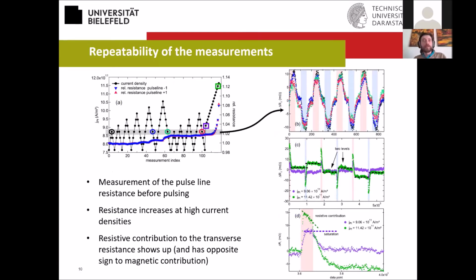Okay, in the literature, there have been some discussions about artifacts in these measurements. So we have been very careful about looking at artifacts in these measurements, and we looked at the repeatability of these measurements. What we did is we looked at measurements at constant current density, but we did cycles. So we increased the current density, decreased it again, increased, decreased, and so on, and always looked at the same current density to see whether our results are repeatable.